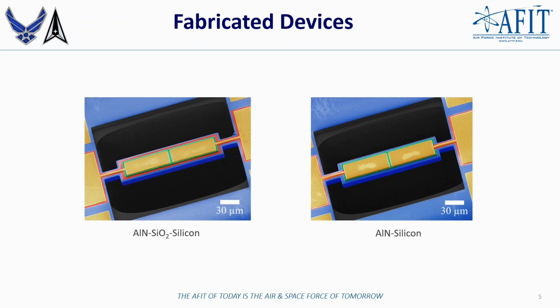Now, on this slide here, we present the colorized SEM images of our fabricated resonators. On the left is the aluminum nitride on silicon dioxide on silicon resonators. And on the right, we have the aluminum nitride on silicon structure without the oxide layer. So we can see the oxide layer is highlighted in red color there, and we don't have any oxide in this resonator. So in both cases, the resonators have been fully released, allowing them to vibrate freely. And again, as we mentioned earlier, the oxide layer there plays a critical role in acting as a buffer layer, smoothing the surface defects and enhancing bonding between silicon and aluminum nitride transducer.